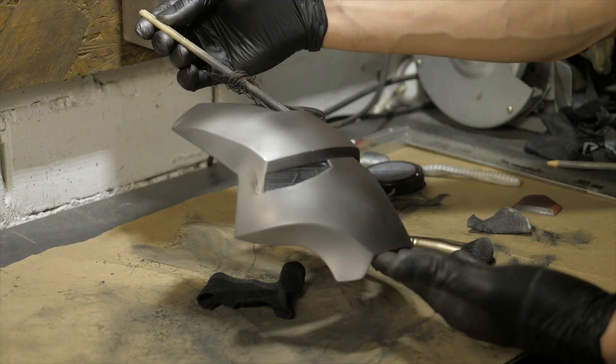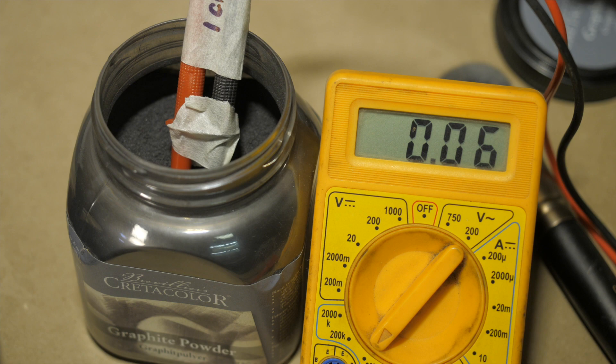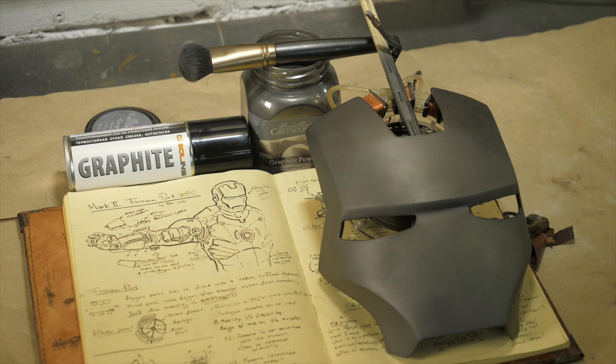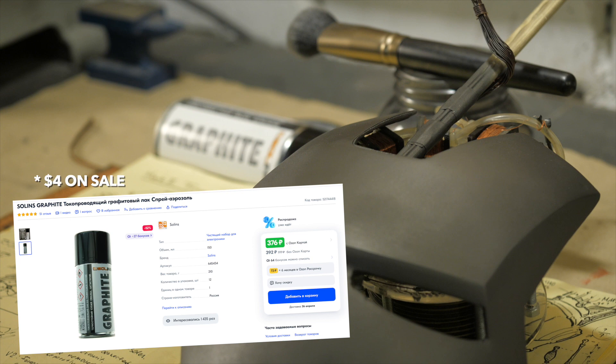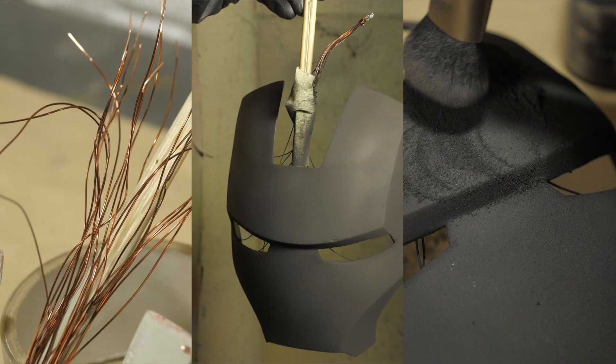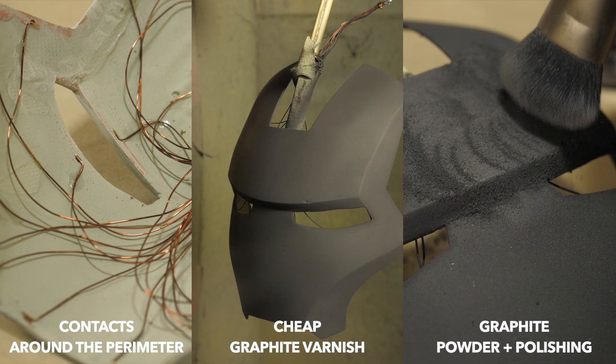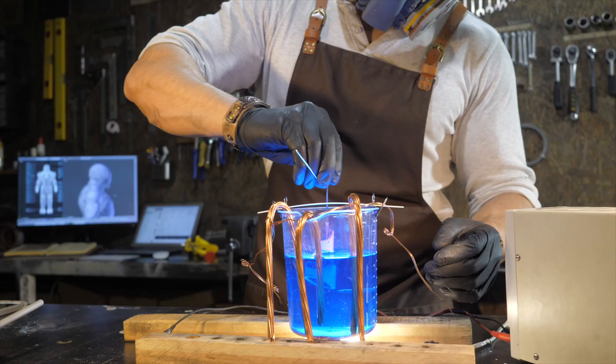With this combination of graphite in the form of varnish and powder, we lower the resistance from 5 kilo-ohms per centimeter to less than 1 kilo-ohm per centimeter. Moreover, the cheapest graphite varnish is also suitable for such a combination for only $7 per 200 grams. And most importantly, this method allows you to achieve a uniform copper coating of a large area without hard-to-reach copper paint. Which means using the electroplating method of applying a metal coating in garage conditions not only for DIY toys, but for large functional parts.